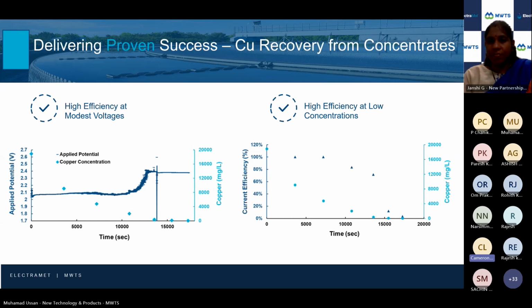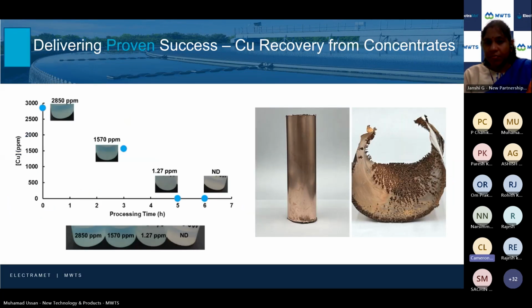So that is the sweet spot of where we want to switch from our Cu recovery reactor to our mid-range reactor. Next slide, please. And that's what we're showing here. So now we developed this reactor that is in between standard electrowinning and better for bulk than our other polishing reactor. So this handles ranges from 5,000 ppm down to 500 ppm very efficiently.